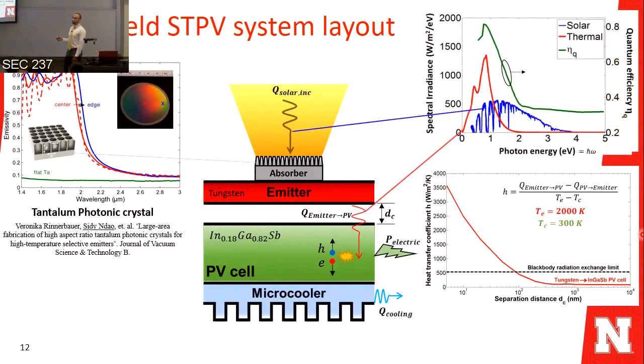And the other advantage of having the absorber emitter between the sun and the PV cell is enhancing the efficiency. How does this work? That's the quantum efficiency of the indium gallium antimonide, the green curve. And the quantum efficiency is just the conversion efficiency at every frequency. At every photon energy, you have different efficiency. You can notice that there is a peak here around 1 electron volt. At this peak, you have the highest efficiency. You wish all your radiation happened at this peak. If you have a laser working at this peak, you will have the highest efficiency possible of these cells.